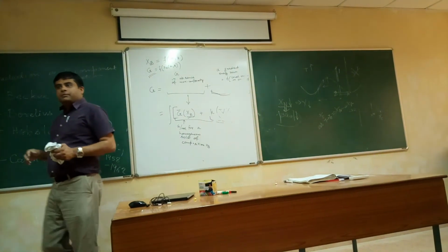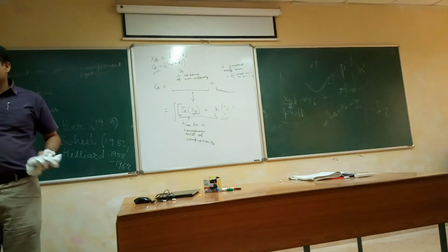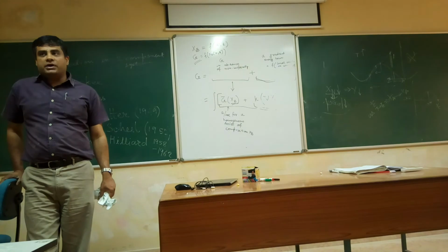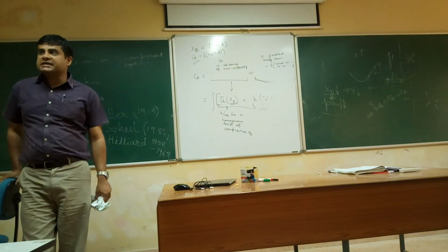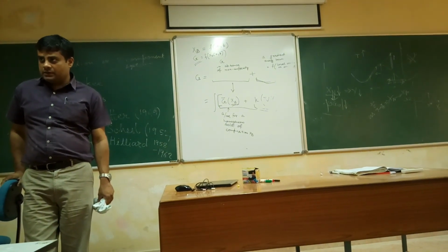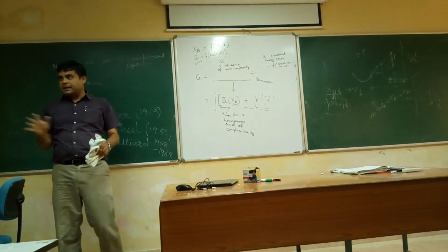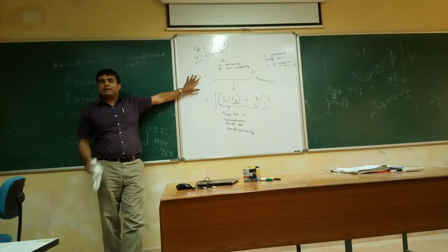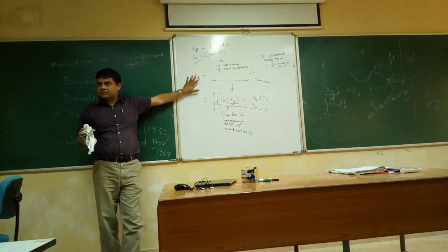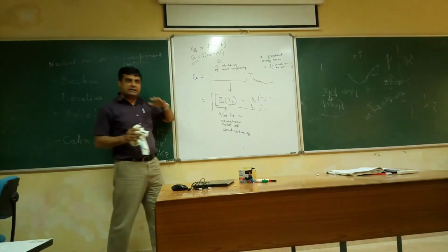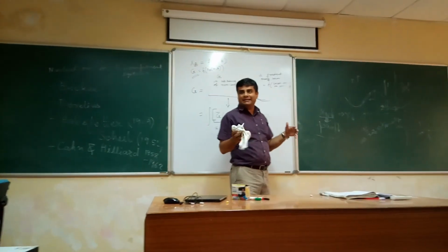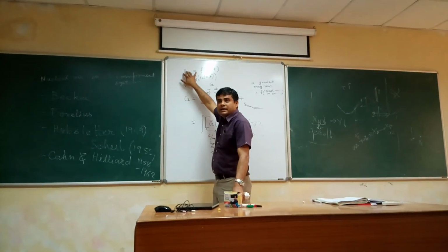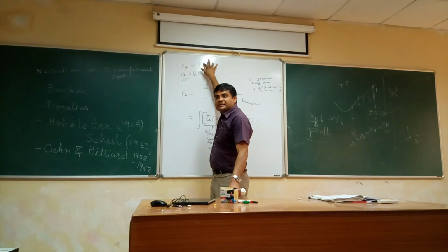You know about phase field modeling? Have you heard of it? So presently all the microstructure evolution modeling is done based on something called phase field modeling, which is based on this Cahn and Hilliard approach. So from these you can write a chemical potential equation. If you have the Gibbs free energy, you can write the chemical potential equation. But only thing is your XB is not a scalar quantity. It's a function of both space and time.